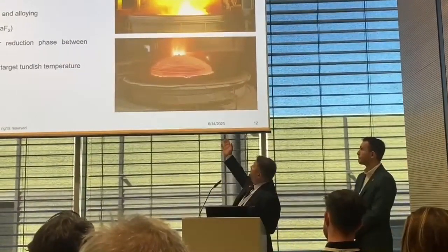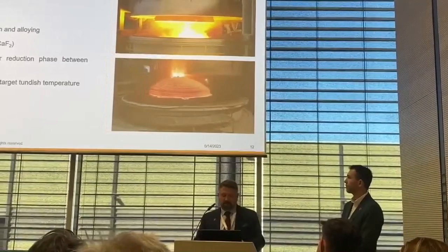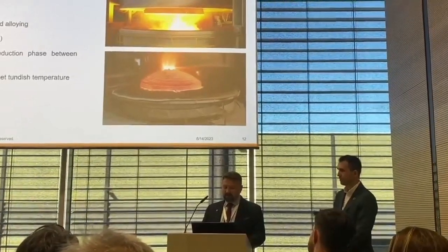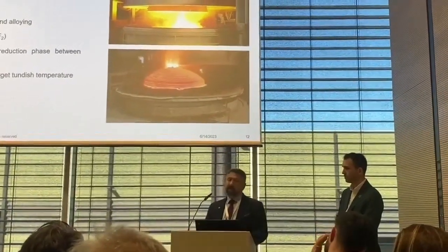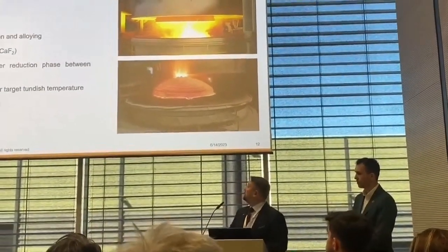The ladle was transferred to the CCM process. And as you can see, I think it is the classical problem for all VOD plants. The steel shell is typically composed of splashing under the roof during oxygen blowing. In our case, its thickness was about 30 millimeters. In the beginning, we tried to cut it by oxygen lance, but it was taking too long. And then we designed a special equipment to remove it.